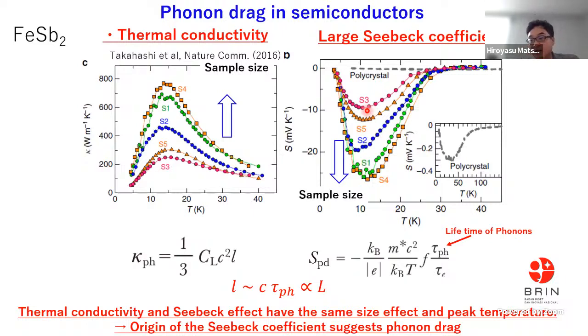If we use a large sample, in this case the Seebeck coefficient is large, and the kappa is also larger. We have sample size dependence. So the thermal conductivity kappa is expressed by these equations. This here is the specific heat of phonons, this is the velocity of phonons, and L means the mean free path of phonons. This is coming from the size of the samples.